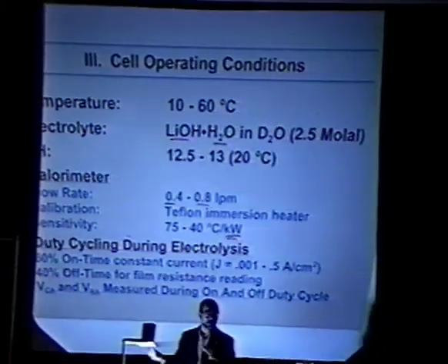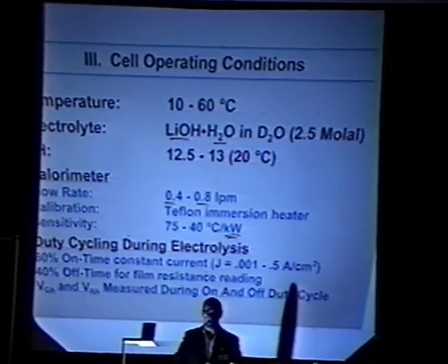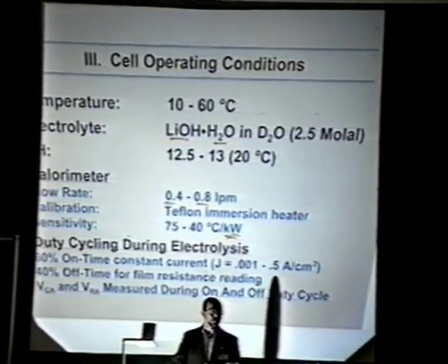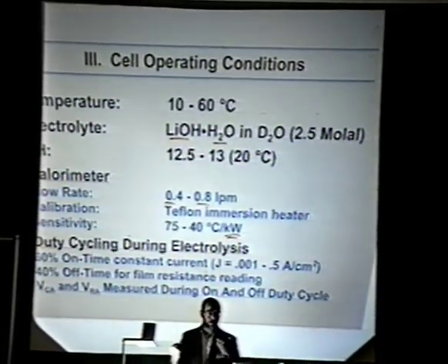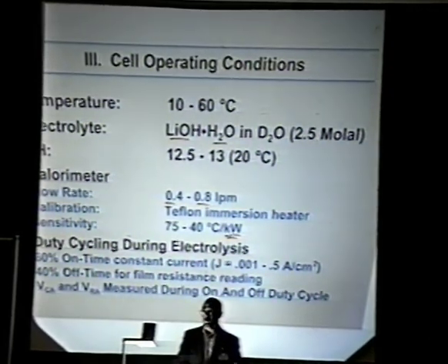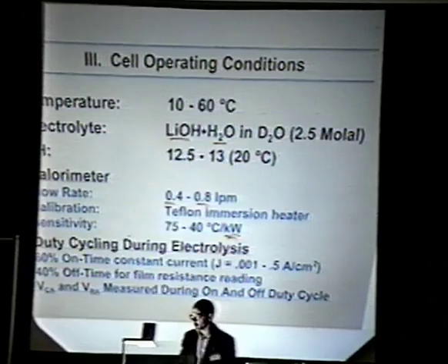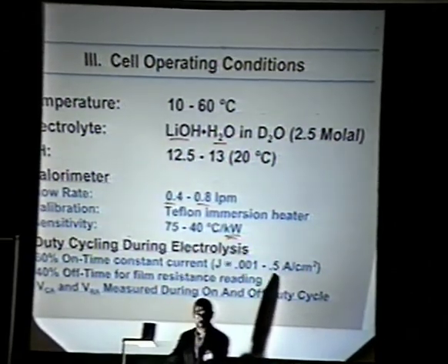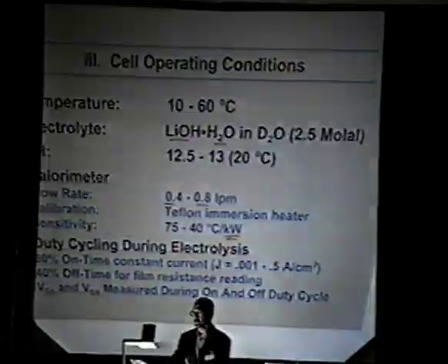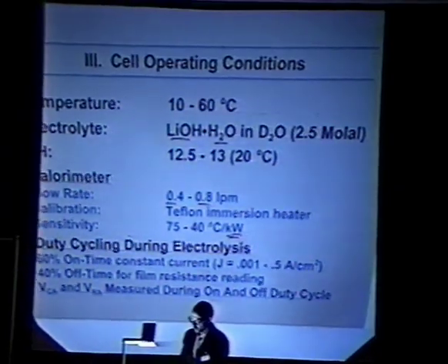And at most, that 0.5 is a very large number, and that's probably on the order of 4 amps DC running through the system. And most of the data today is more in the 100 milliamps per square centimeter, and maybe even 50 milliamps. You'll see various ranges. But typically, if you get up to this level, you're just blowing away a lot of hydrogen and oxygen. So I try to stay a lot lower. Okay, so those are some operating conditions that I think are quite useful.